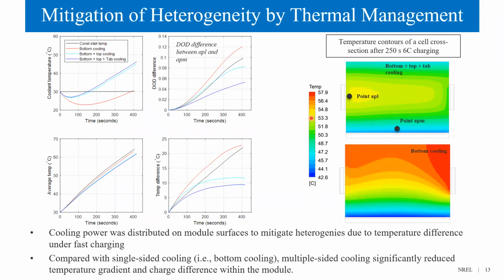For the same cold plate modeling scenario, we continue to use this module and investigate cooling on multiple surfaces. The heat generated by the cell was shunted to multiple cooling plates. During this study, we found significant heterogeneity mitigation was achieved by cooling the cell on multiple sides, as shown. The cooling power for each simulation was held constant, except for the constant inlet temperature case, which assumed the inlet temperature was maintained at 30 degrees Celsius.